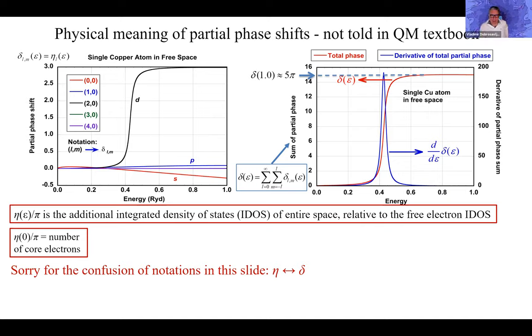What I find a little confusing here is that you talk about core electrons and valence electrons as if they were different things, but from the point of view of Bloch's theorem, they're not different. In a solid you have bands, and it's not obvious to me how you split the bands into what you call core and not core. They're all bands and they have gaps. For a free electron with one local potential scattering problem, either you have a bound state or a scattering state, a clear-cut distinction. But in a solid, the scattering states in the conduction band can also open gaps, so you have discrete bands everywhere. I don't understand how you can cleanly separate bound states and scattering states in a solid.